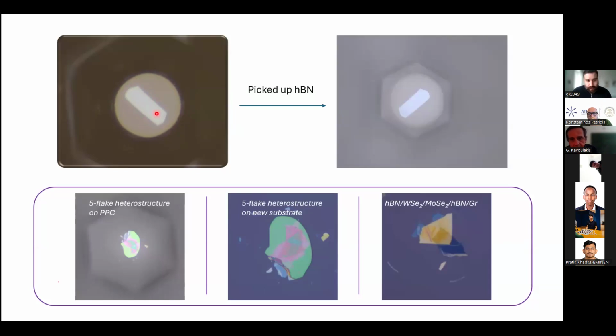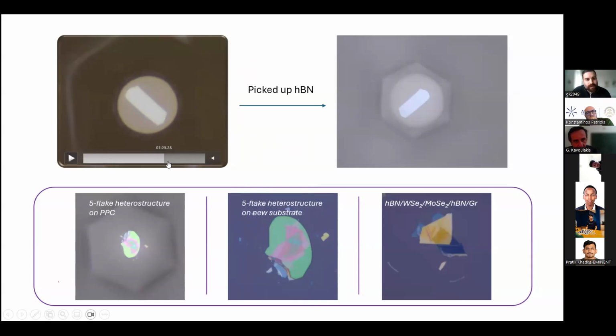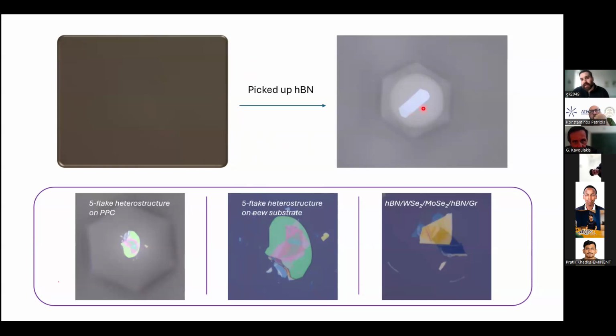And you can see this process here. It's a fast forward, let's say, video, relatively fast. So it's starting already to retract. We have full control because the motorized stage will move based on the code at very slow speeds. And we can stop and keep going anytime we want. And you will see here, maybe fast forward this, that until the end, we maintain control and shape of the contact front. And you will see the flake transferred on the pillar here.